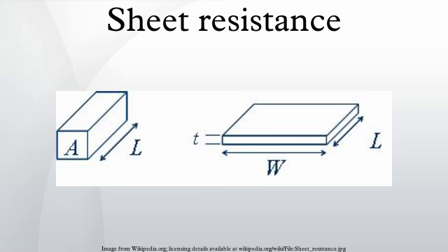Measurement. A 4-point probe is used to avoid contact resistance, which can often be the same magnitude as the sheet resistance. Typically a constant current is applied to 2 probes and the potential on the other 2 probes is measured with a high-impedance voltmeter. A geometry factor needs to be applied according to the shape of the 4-point array. 2 common arrays are square and inline. For more details see Van der Pauw method.